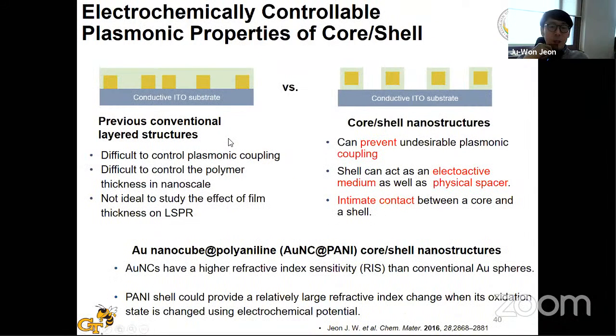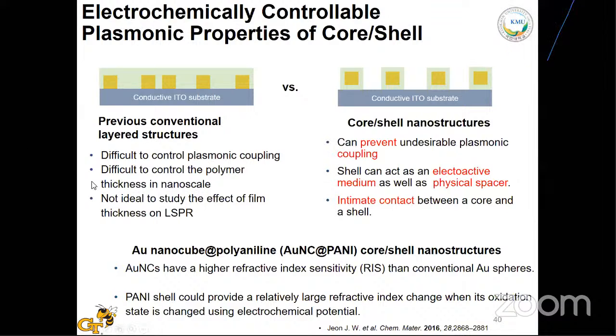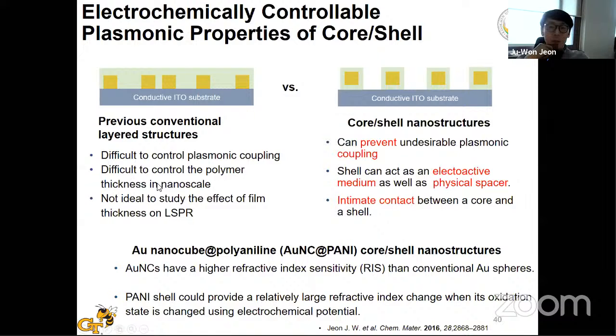In this study, we were particularly interested in core-shell nanostructures for real-time control of the LSPR property, because of their advantages over the conventional layered structure. In the conventional layered structure that was published before, it is difficult to control the plasmonic coupling. If the plasmonic nanoparticles touch each other, the original plasmonic property disappears, and the aggregated LSPR property will emerge. It is also generally very difficult to control the polymer thickness at the nanoscale. If you want to control the thickness at the 5 nanometer or 10 nanometer scale, it is very difficult to do so with that accuracy. So it is not an ideal system to study the effect of film thickness on the LSPR.